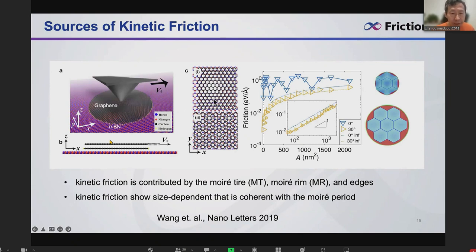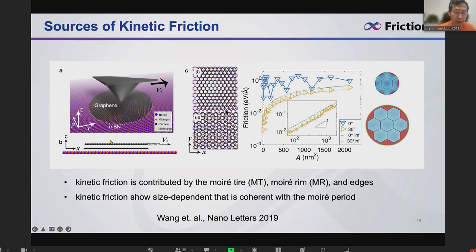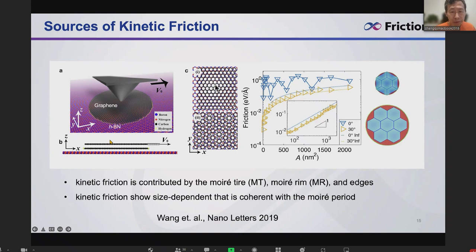For fully 2D material contact, we found we can estimate contributions from moiré patterns — both moiré tire and moiré rim contribute. However, if the size is limited to the micro scale, all these contributions are negligible. My conclusion is: at micro scale, friction comes majorly from the edge; the inner area contribution can be ignored. This holds from both theoretical and experimental research.